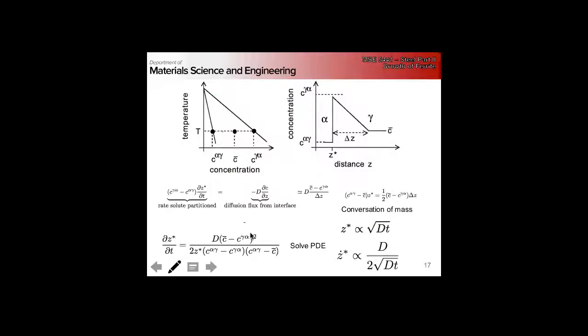And we get a PDE that looks like this for the change in the position of our interface with respect to time as a function of our diffusivities and our concentrations and the current position of the interface.